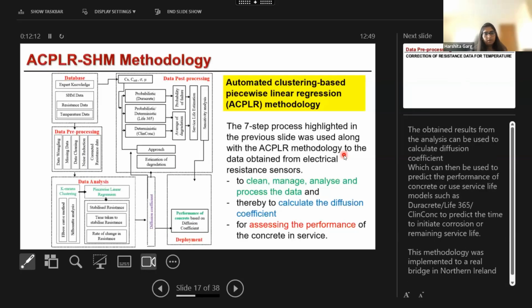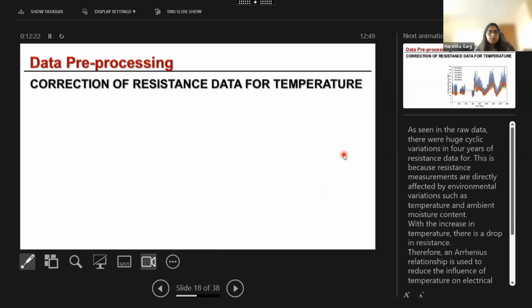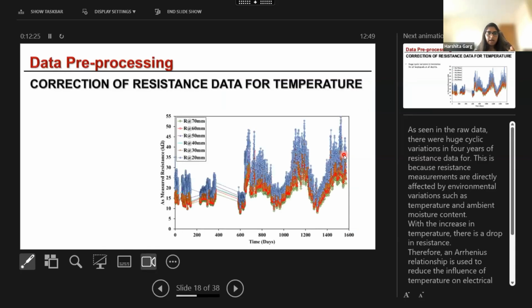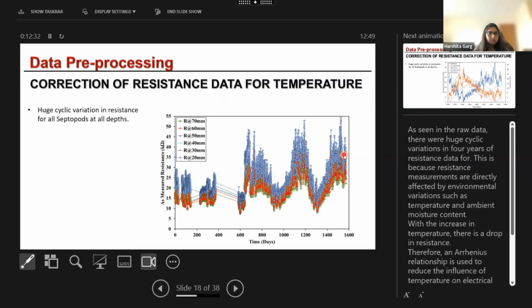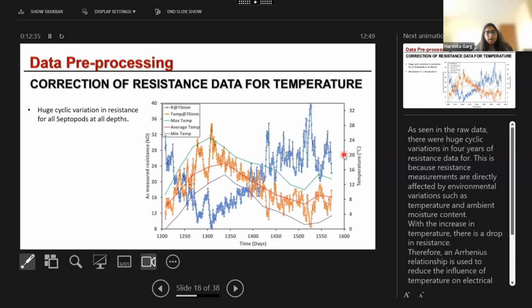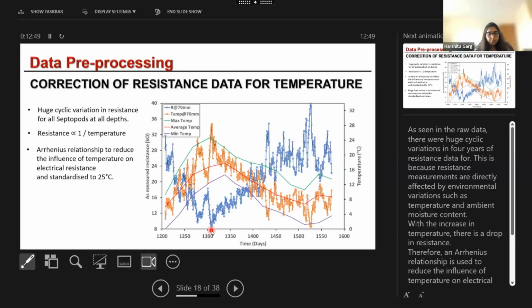All these steps I will now discuss on the sensor data that we got from the Abercorn bridge. The next step was to pre-process the data, and here we can see that there were huge cyclic variations in 4 years of data. This is mostly because resistance measurements are directly affected by environmental conditions. If you see, with the increase in temperature, there's a sudden drop in the resistance. So an Arrhenius relationship was used, which reduces the influence of temperature on electrical resistance and standardizes it to 25 degrees Celsius.